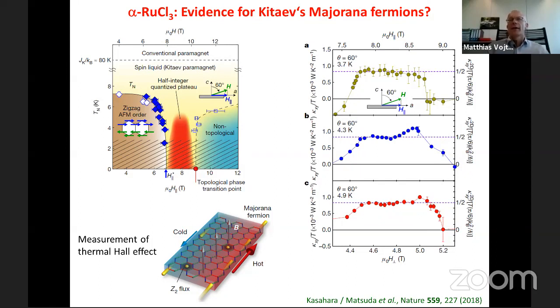Which means the interpretation of this experiment is highly non-trivial, because you have a large bulk heat conduction, which is conventional. So there's a large kappa xx, so a longitudinal heat conduction. And there's only a small transverse heat conduction. And this is the one which is extracted here. So in other words, even if there is a quantized edge mode, it's absolutely non-trivial to see a quantized Hall coefficient at all, because the bulk is not insulating.